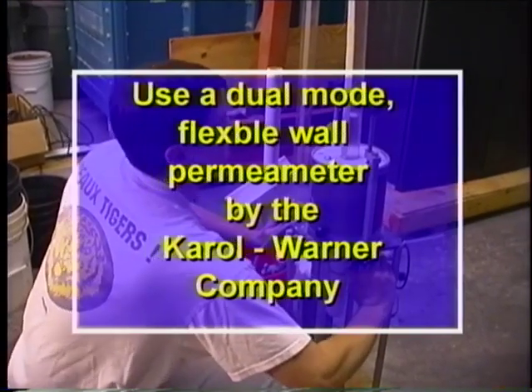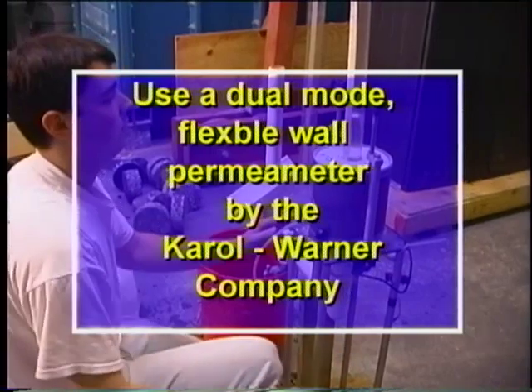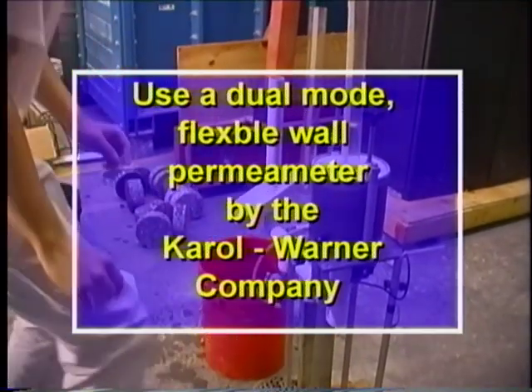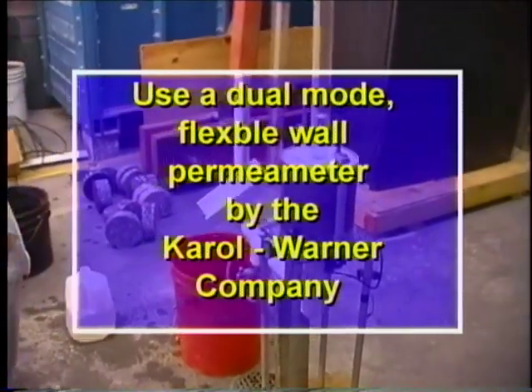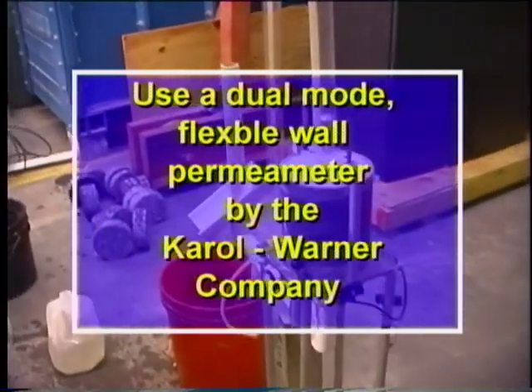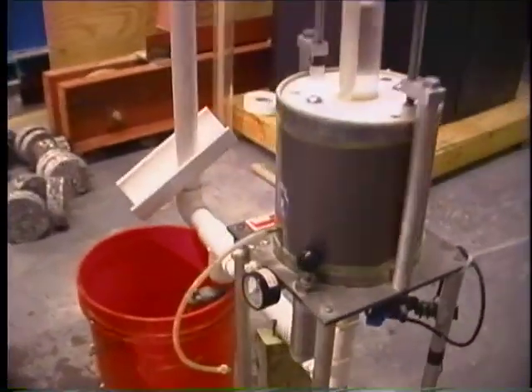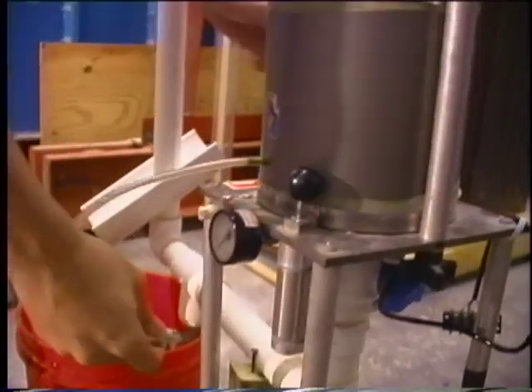Perform the permeability test using a dual-mode flexible wall permeameter from the design by the Karol Warner Company. Place a 6-inch sample in a chamber and allow water to flow through it. The rate of flow is then measured to determine the permeability.